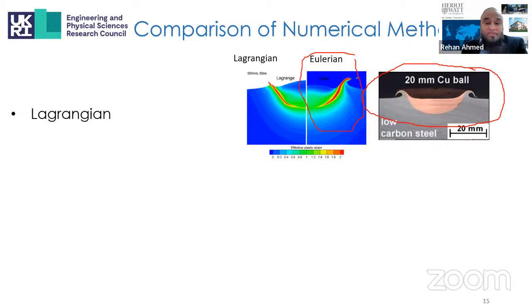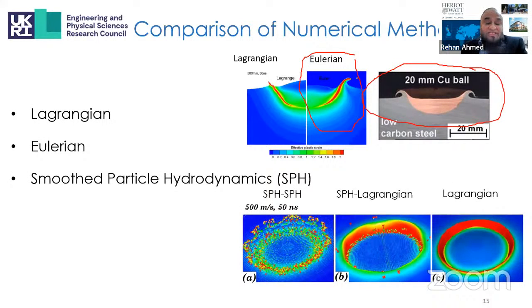Smooth particle hydrodynamics has been successfully applied to model high strain rate deformations. However, challenges remain in acquiring the correct combination of material parameters and particle connectivity. So the image shows a back-to-back comparison of modeling using a pure Lagrangian, a smooth particle hydrodynamic as the particle in the substrate, and then smooth particle hydrodynamic alone, or on its own kind of modeling.